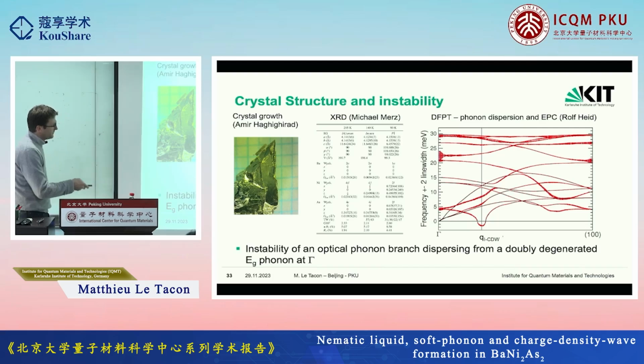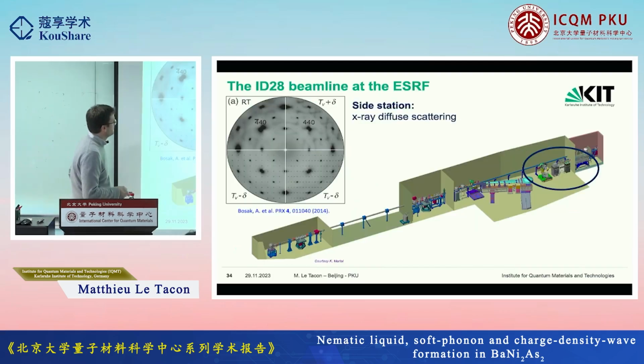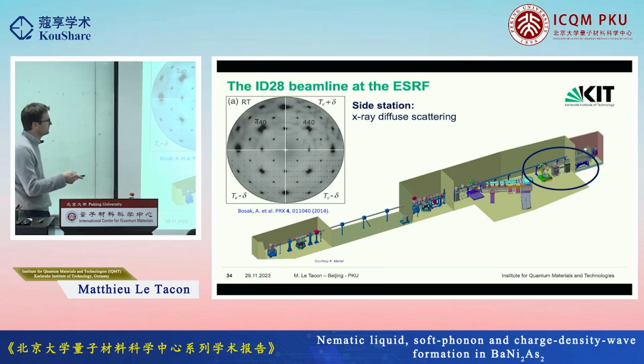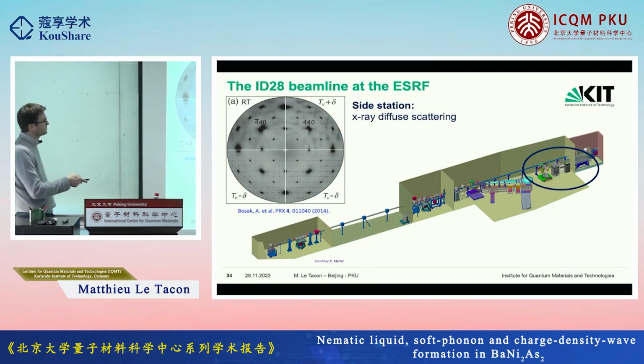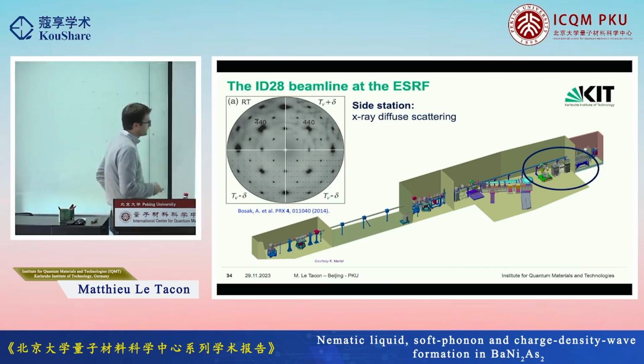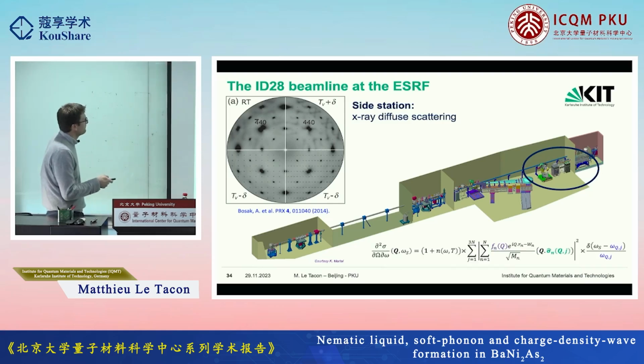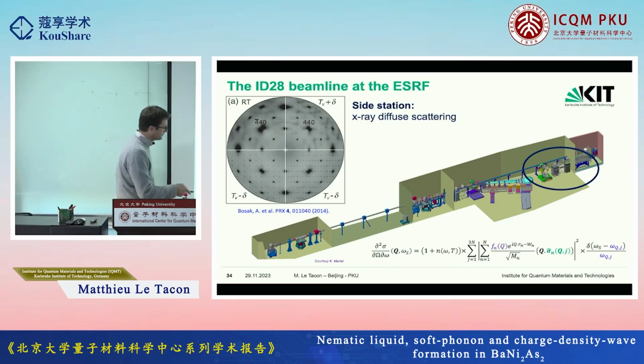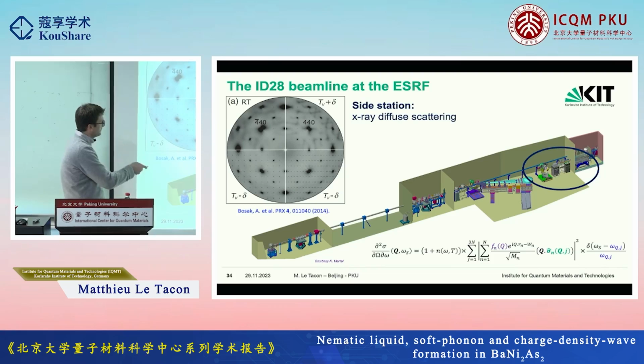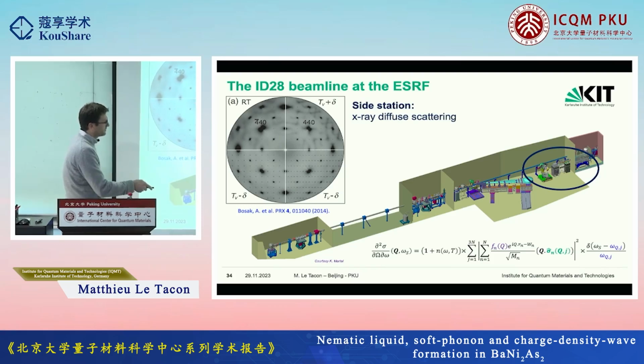Now we had this prediction of these unstable phonons, and we thought it would be good to check. For this, what we did is to use the inelastic X-ray scattering beamline, but the side station of that beamline, which can be used to do X-ray diffuse scattering. This pretty much consists in looking at what's happening between the Bragg reflections. What you do when you do this inelastic X-ray scattering experiment, you look at the dispersion of some phonons. So this is your scattering cross-section. I explained it better yesterday, but in short, you have a form factor that modulates the intensity across the Brillouin zone. You have this polarization selection rule, in a way, which allows you to select the phonons which are polarized along the momentum transfer you're looking at.